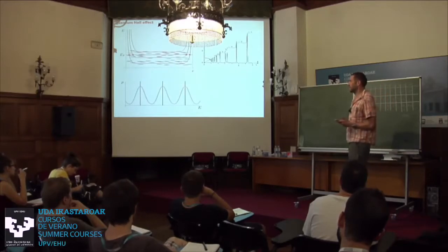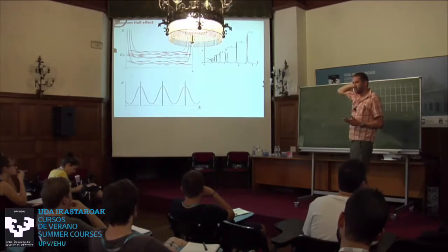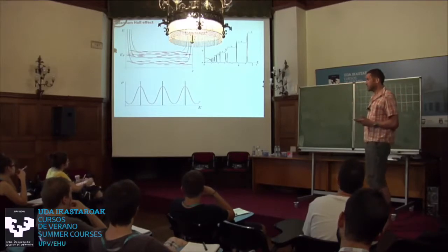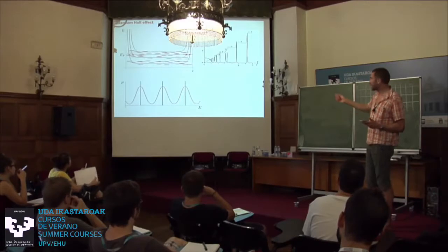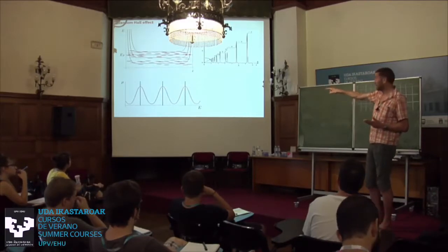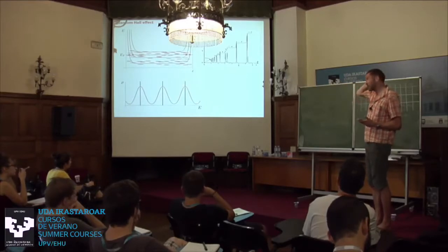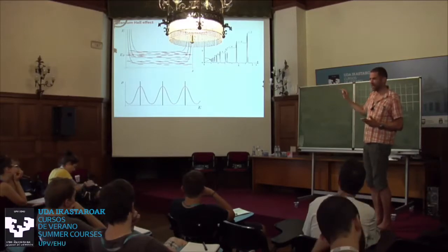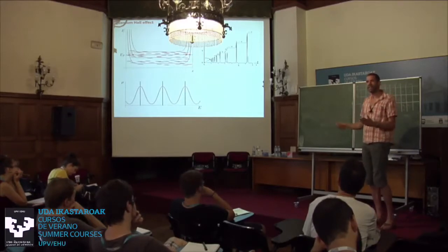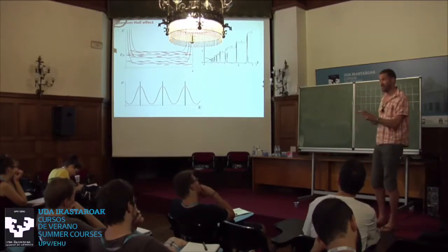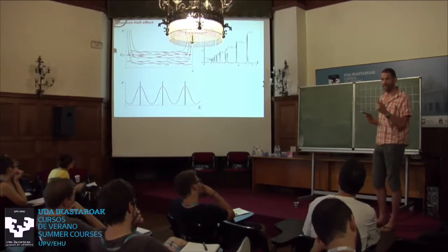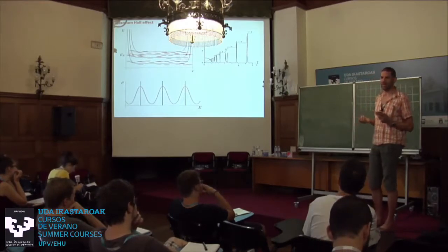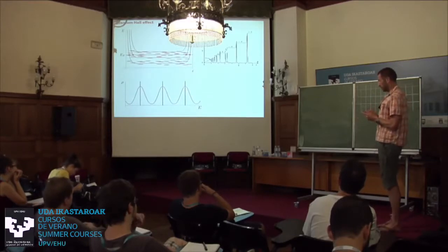People observed that a typical quantum Hall sample is never clean. There are impurity states in the middle which don't care about the position of the Landau levels. And that means that on average, if you average over configurations, the density of states is actually smooth as well. So the red curve down there, and the important message I want to convey: there is no gap in the system. The system doesn't have any kind of spectral gap. Often we hear that a topological insulator is stable as long as you have a spectral gap in the spectrum, but in reality that's nonsense. There are never spectral gaps, never ever. Even for weak disorder, you always have tail states. So we ought to explain topology eventually without reference to gaps. Okay, so that was that.